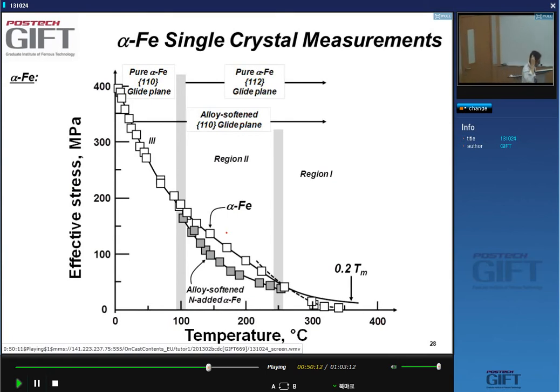So this is the other thing that's important for iron: depending on the temperature, you'll have different slip planes. So if you plot the temperature and you plot what we call the effective stress, that means you only plot the temperature-dependent part of the shear stress. That's why it looks here like the stress is zero at room temperature. It's not zero. We just removed anything that was temperature-independent. Okay,